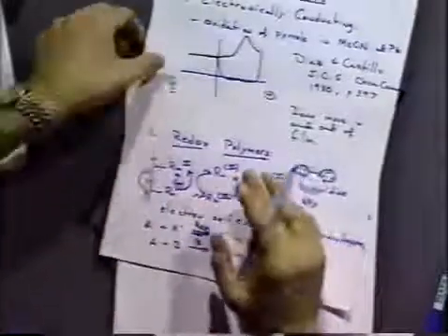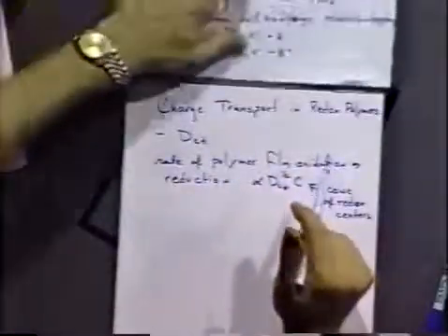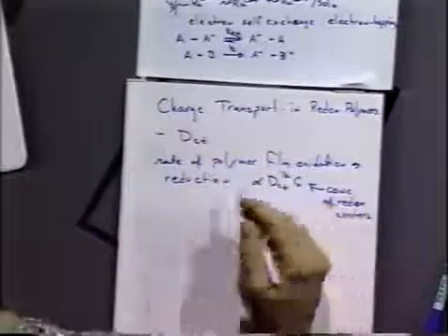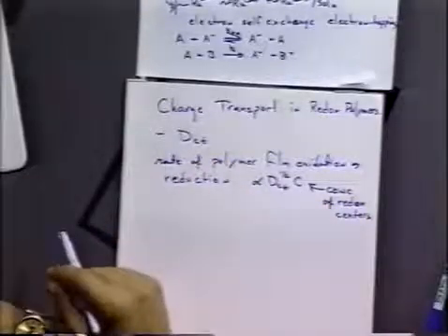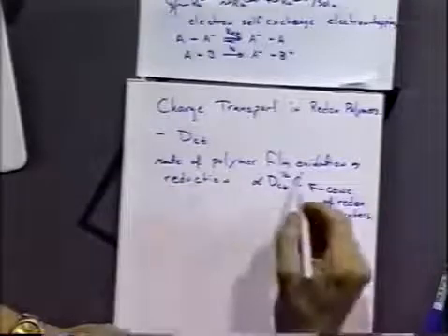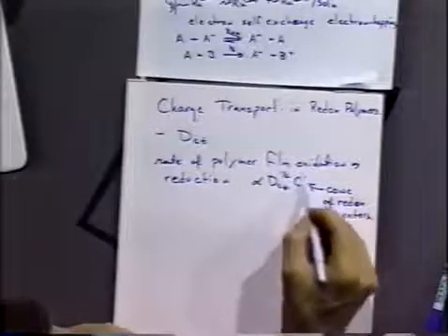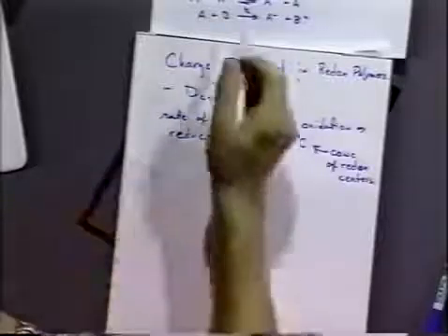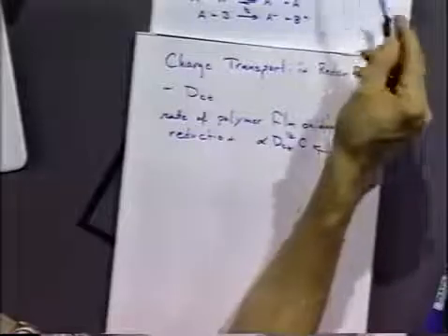We can study that rate by putting together a fictional diffusion coefficient, which is a reflection of the rate that the charge transport moves through there. Not assuming a mechanism of movement of charge, but assuming that it does move, we can assign a diffusion coefficient to it, and multiply that by our number of redox centers. We can calculate that by knowing, for example, how many bipyridine groups we've attached to the polymer backbone per a certain number of carbons otherwise.